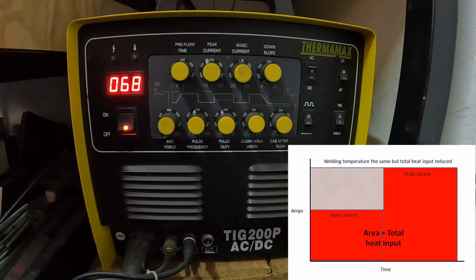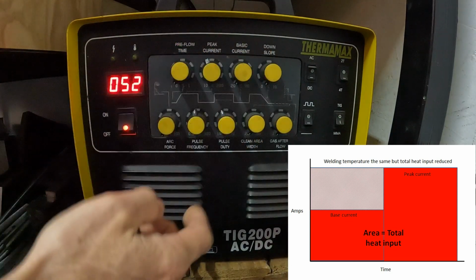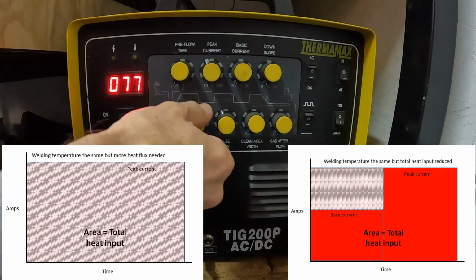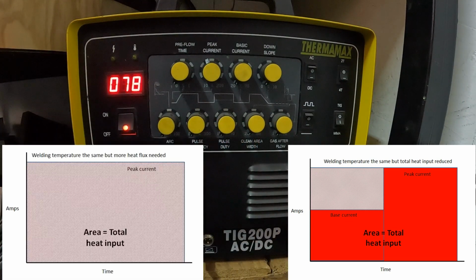But let's take another material like copper, for example. Copper's got a much lower melting point. It melts at about, say, 1090 degrees, depending on certain conditions. But the conductivity of copper is much, much, much higher than stainless steel. So everyone knows that you can't weld copper at 60 amps. It just won't work. You won't get a weld pool. You need to do two things. You need to preheat, and you need to have all the weld inputs. In other words, you can't have a basic current. You need to set that to 0, and you need to have a DC current. So then your pulse frequency and your pulse duty aren't helping you at all. So basically, you're putting as much heat as you can into that weld pool.